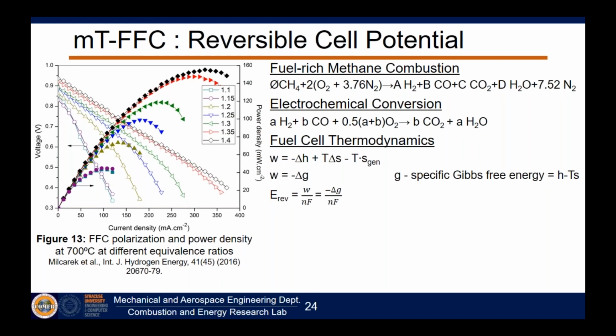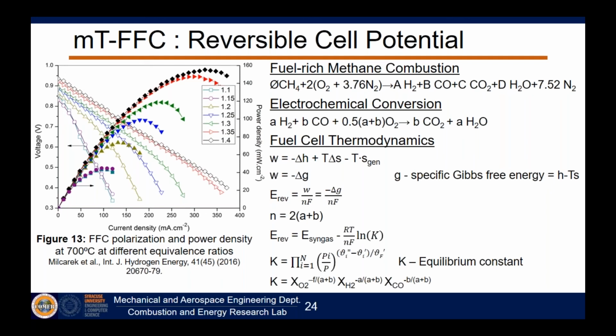Now in our case, we can find delta G because we know the composition of the fuel. We also know that n in this case is going to be related to the dilution, right? Normally it's 2. We have 2 moles of electrons per mole of hydrogen, same for carbon monoxide. But in this case, we have very diluted fuel. There's only a little bit available.